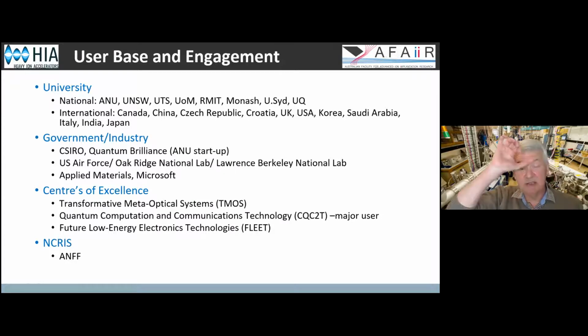Quantum Brilliance is an ANU startup based on quantum sensing and quantum computing using the NV Centre in Diamond. And actually their production at the moment is based on the use of our facilities. They use the low energy implanter for the quantum sensing activities where you need the active center, the NV center, to be close to the surface of the diamond. And they use the high energy implanter to bury the NV centers deep in the diamond for quantum computing.